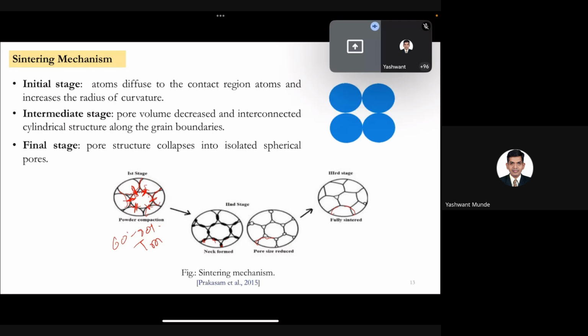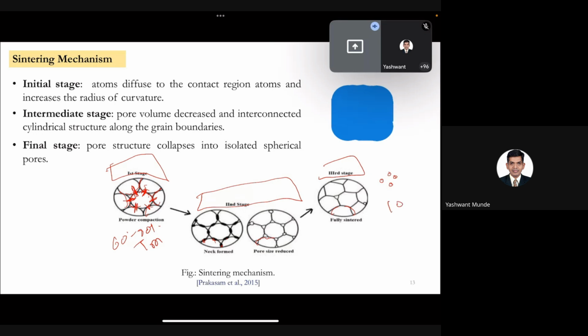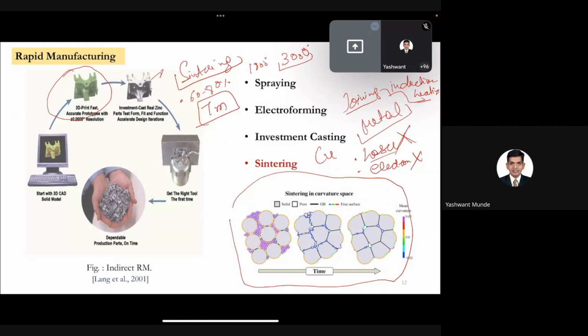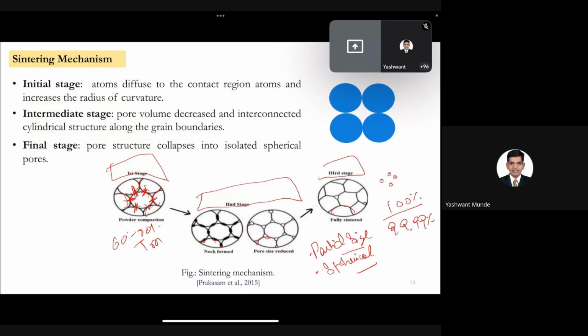So this is called the first stage of sintering, and this is called the second stage of sintering, and at the final end there are very small round pores. So it is the third stage of sintering. In sintering, it's very difficult to get a 100% dense part. You can go maximum up to 99.99%. There are a lot of factors like your particle size and your particle geometry, whether it is spherical or not. There are a number of factors which affect the density of the material. So when we are dealing with sintering and 3D printed parts, we need to see when we can get this third stage, because our optimum goal is to get a highly dense structure.